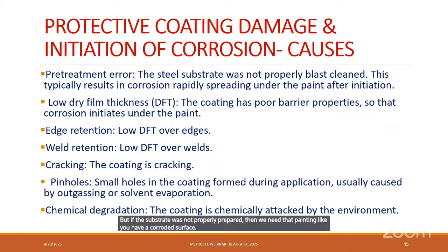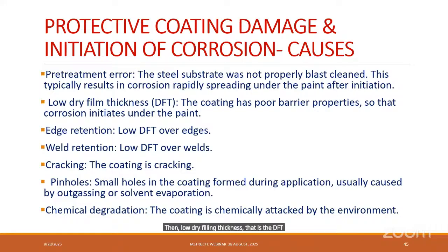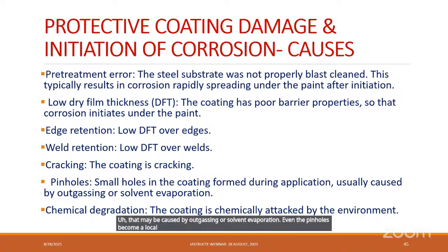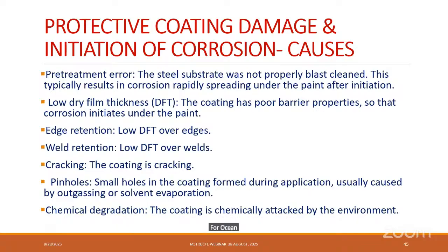Then low dry film thickness, that is the DFT measurement, that is important. So the coating has poor barrier property if you have a low dry film thickness. So the corrosion again initiates under the paint. Edge retention, low DFT over edges, weld retention, low DFT over weld, or cracking, that is the coating itself is cracked, or there are some pinholes or small holes in the coating during application that may be caused by outgassing or solvent evaporation. Even the pinholes become a local point from where the corrosion initiates.